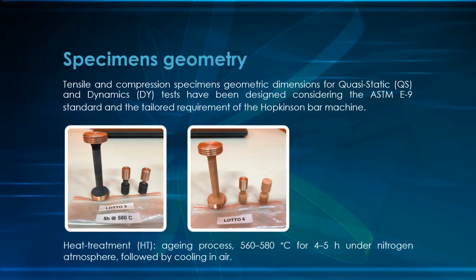Here you see the different specimens produced for the research. So we produced tensile and compression specimens. Those specimens have been designed on the ground of ASTM standard and on the ground of the requirement of the Hopkinson bar machine used for dynamic tests. Part of those specimens were initially heat treated, as suggested by the powder producer, at 560 degrees centigrade for 4-5 hours under nitrogen atmosphere.